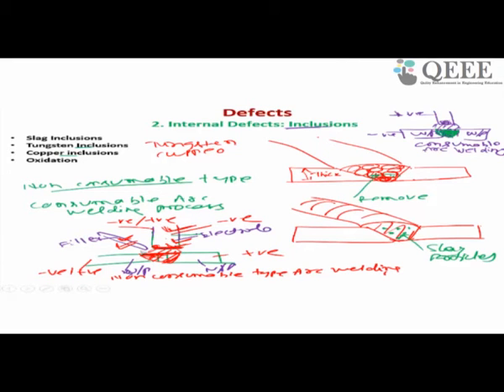What is this inclusion? It is tungsten inclusion or copper inclusion. These particles break from the electrode and fall in the weld pool, and inside the weld pool they will not be visible. If the particle size is very small, maybe a few microns, small particles of the electrode may break and deposit in the weld pool. That is called inclusion.